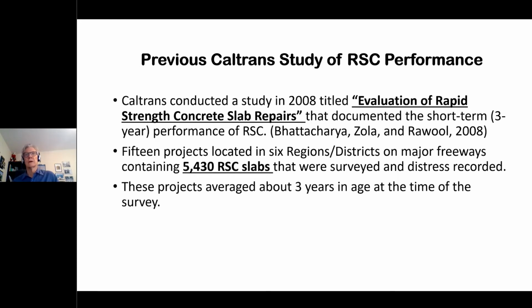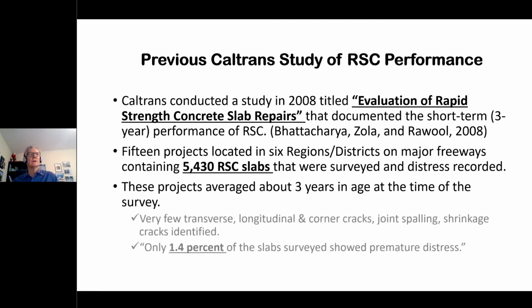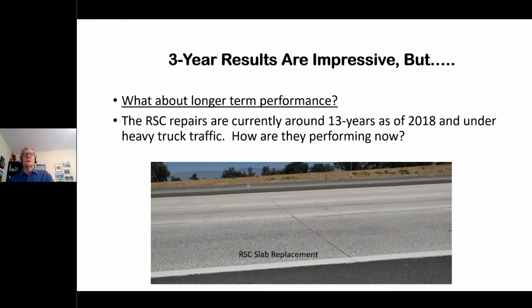These projects, again, averaged just 3 years of age, but they found very, very few transverse, longitudinal, or corner cracks, joint spalling, shrinkage cracks, or anything else like faulting. None of that. And their conclusion is only about 1.4%. That's like 1 out of 100 slabs surveyed showed any of these, what they call premature distresses. So that's really impressive. But what about the longer term, of course?